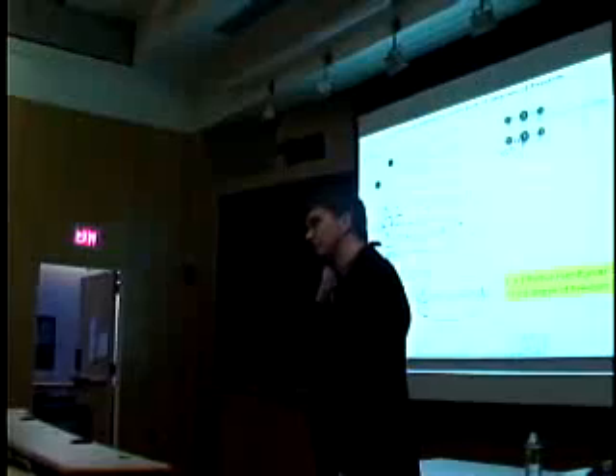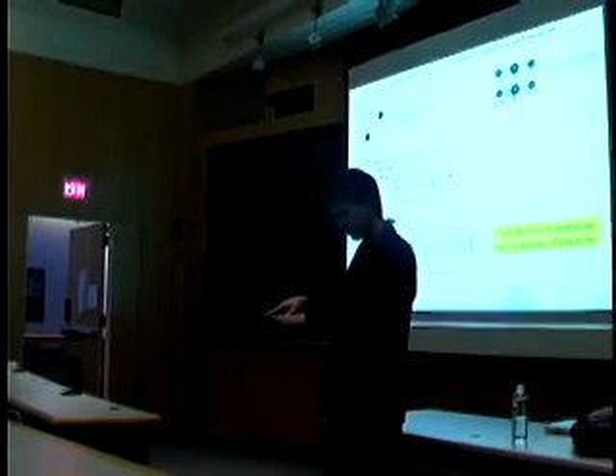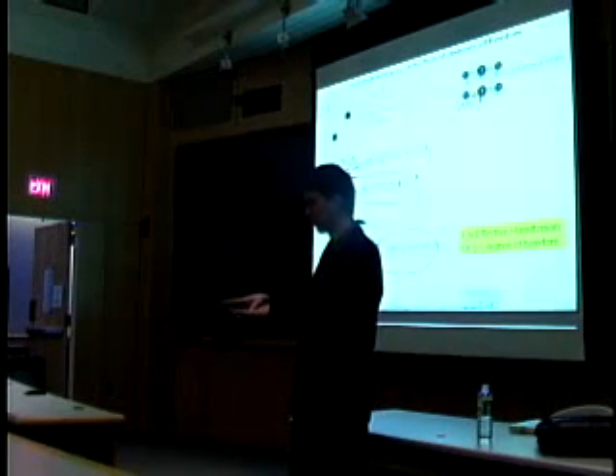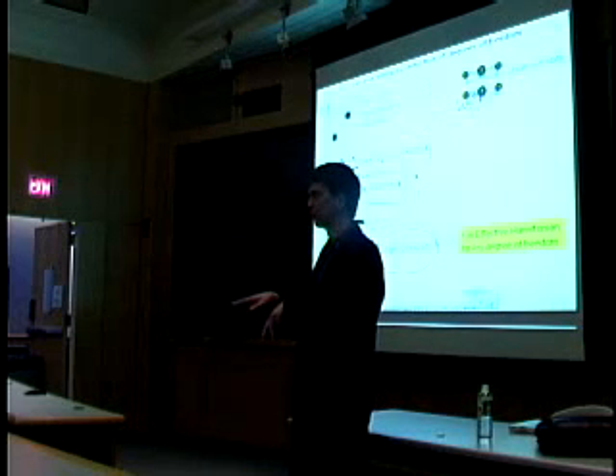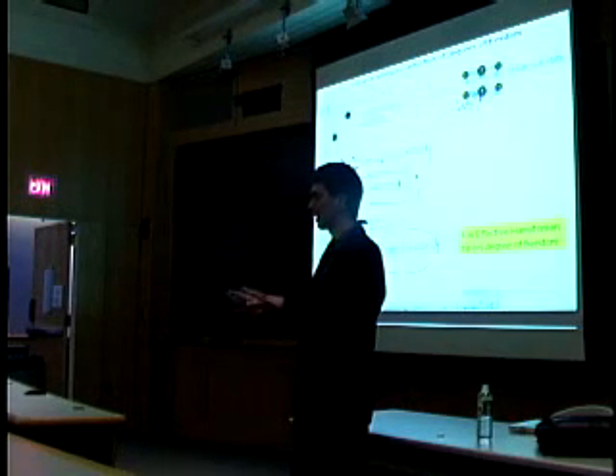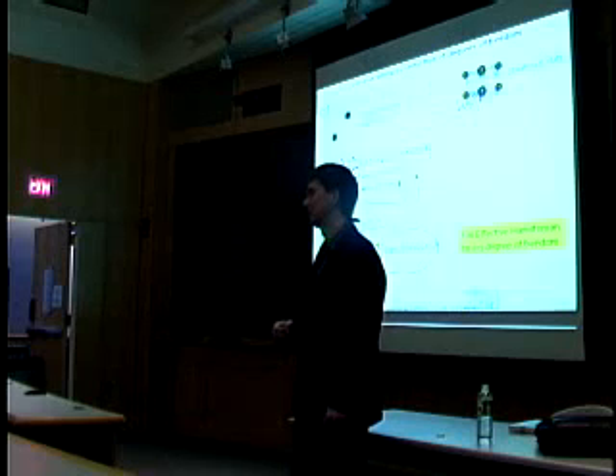Because let's say I'm going to do it this way. So let's say on this I do Monte Carlo now. There is a small assumption that I've made in all of this. Think of the physical picture here. Essentially what I'm saying is that I've got these A's and B's sitting on, you can't call them exactly lattice sites, but they're associated with a given lattice site. They may be displaced from it. And they sort of vibrate around, and I integrate those vibrations to get the vibrational free energy. And then once in a while they hop, exchange, and if I sample that, that gives me the free energy coming from that slower time scale. There's one assumption I've made in all of this. And it's a subtle one, but I've essentially assumed that the time scales are uncoupled.